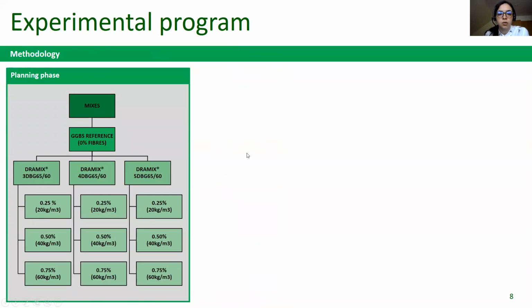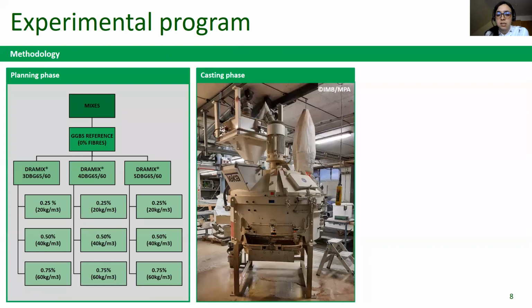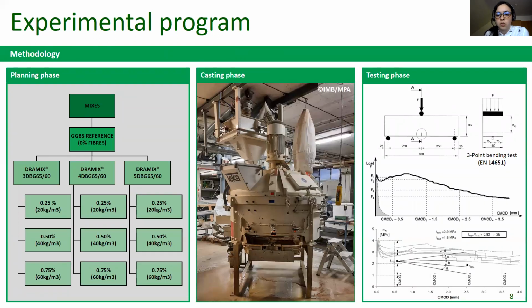This research work was defined following three different phases. A first planning phase in which binder, mix design, fiber type, and volume fraction were defined. A casting phase in which all the samples were prepared, and a testing phase in which the samples were tested according to European standards. Cubes were tested to evaluate the compressive strength development over time, and 3-point bending tests were performed to evaluate the flexural post-cracking behavior of the composite.